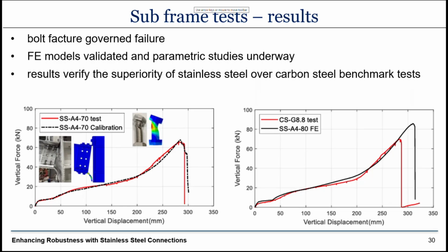In all cases, bolt fracture governed failure. No angle cleat fracture was observed. Finite element models were validated and parametric studies, some were completed, some are underway. The results verify that for a stainless steel specimen, we have higher strength and a bit higher deformation compared to a carbon steel specimen.